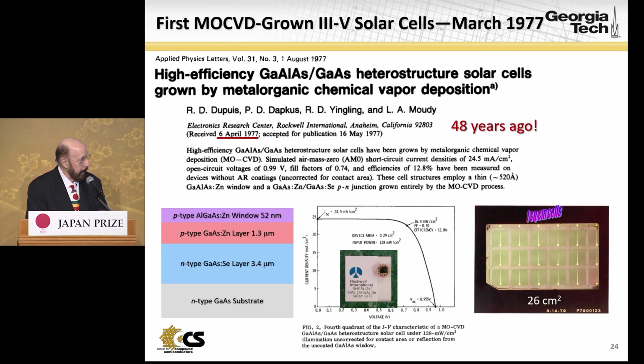What you see in the panel on the far right is what we consider a large area wafer, 26 square centimeters. It was the largest piece of high purity, high quality gallium arsenide we could buy at the time. These were float zone crystals, and they weren't very large, but you can see this is an array of 5 by 3 1 square centimeter solar cells fabricated on a single piece, which at the time this work was done in 1977 was the record.